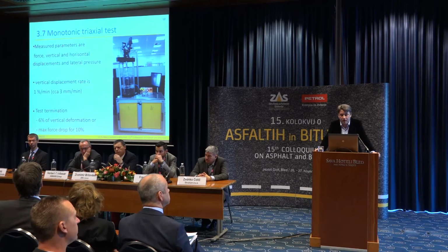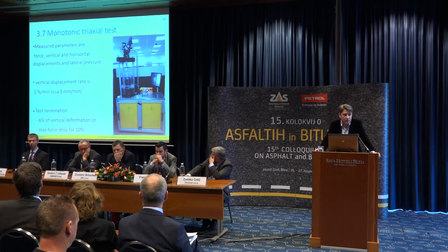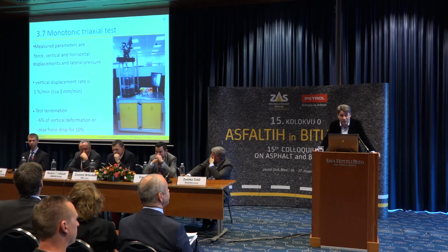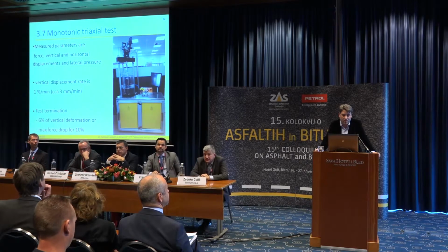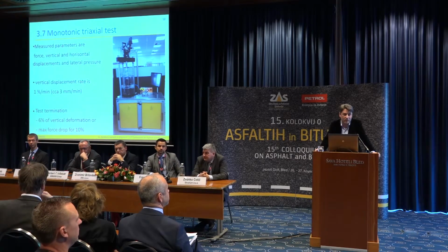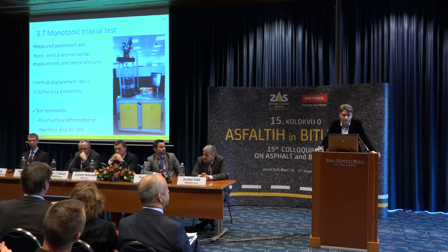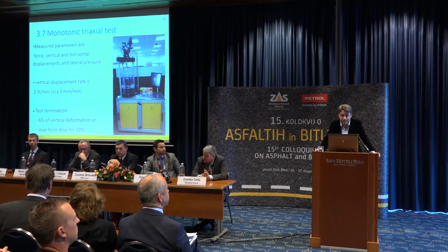Finally, when you get to this point, you're really happy that you have your sample in one piece. You need at least 8 samples, or 12 better, and you split them into four groups, and each group is tested at a different sigma 3 lateral pressure.